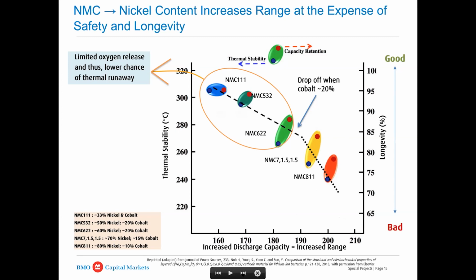element to replace. What happened earlier on in research was that they tried nickel-only cathodes and they just exploded. So then they started adding things like manganese and cobalt and aluminum, and they're trying all these things. And so I view nickel now as the star. Nickel's the star. Cobalt, manganese, aluminum, all these other elements, and even iron. They're doping, switching out cobalt and adding iron as well. So it's an NFA. All the other elements are basically trying to keep nickel from getting into trouble.